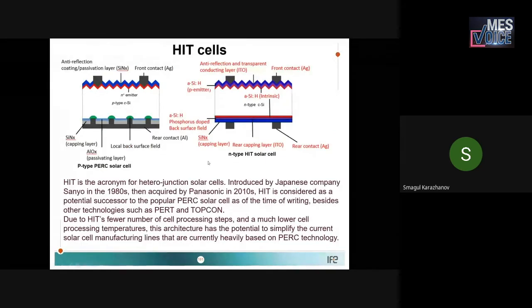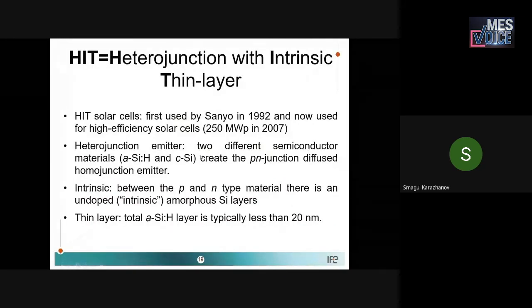And another very popular and emerging type of solar cell is called the HIT cells. HIT is an acronym for heterojunction with intrinsic thin layer solar cell. This was developed by Japanese company Sanyo in the 1980s. And why is it heterojunction? Here, amorphous silicon is used that possesses a different bandgap than crystalline silicon. So here it's heterojunction. The advantage of amorphous silicon is that it is used for making a p-n junction with silicon on the one hand. On the other hand, it can passivate the surface well. And intrinsic amorphous silicon is used also, which is why it's called heterojunction with intrinsic thin layer. And this intrinsic thin layer is of thickness of about 20 nanometers.